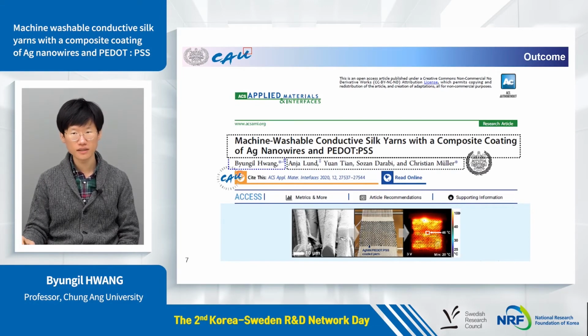We did quite intensive collaboration and had a nice result. We could develop machine washable conductive silk yarns with excellent conductivity by applying silver nanowires. With this result, we published a quite nice paper in ACS Applied Materials & Interfaces in 2020, titled Machine Washable Conductive Silk Yarns with a Composite Coating of Silver Nanowires and PEDOT:PSS. There are a few more research projects in progress together with Professor Müller's group and other groups at Chalmers, but today I'd like to give details only for this result because of the time limit.